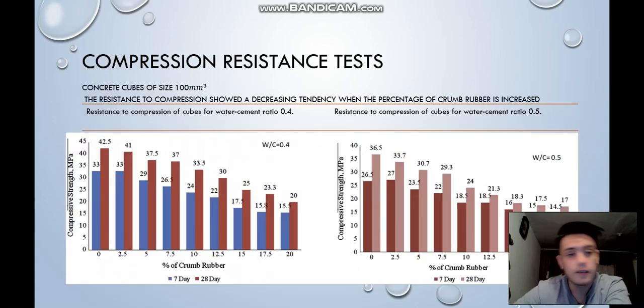Compression resistance test. In this table we can see the compressive strength in megapascals against the percentage of tire dust for the water cement ratios 0.4 and 0.5. Samples were taken at 7 days and others at 28 days, where it was noted that the lower the amount of tire powder, the greater the compressive strength, and that the 28 day samples had greater strength, for water cement ratios of 0.4 and 0.5.